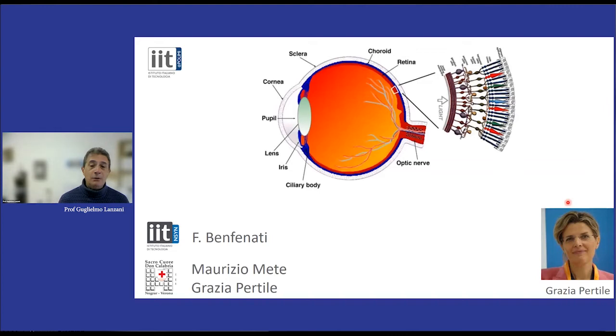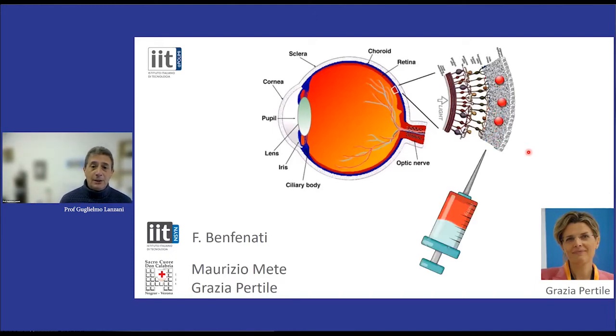So the scheme of the approach is the following. Assume that this is the retina, assume that degradation is occurring, degeneration is occurring, and then the layer of the photoreceptor disappears. Essentially, you do not see them anymore. When the disease starts, they disappear. Then what we do is we inject a nanoparticle in the place of the photoreceptors, so in the subretinal place. And then we go to test the result.